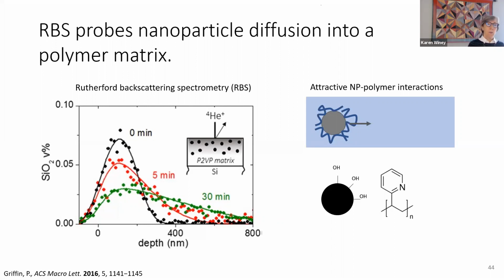In this case, we're using an attractive system where the nitrogen in the poly 2-vinyl pyridine likes to stick to the OH groups. And it's well established that there's an attractive bound layer on particles when you have this attractive interaction. And that's been shown by segmental dynamics at the surface.